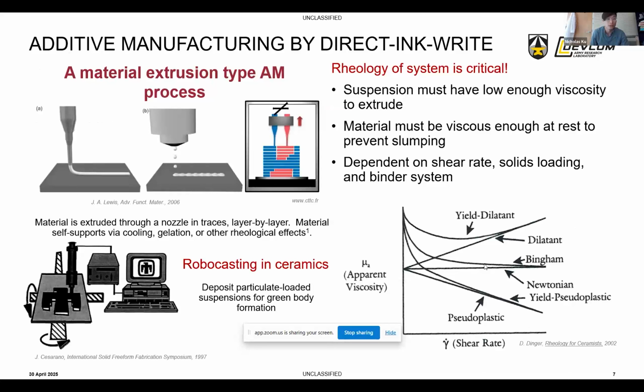So being a direct ink writer, material extrusion type AM process, we do a lot of feedstock development and understanding the rheological behavior. Definitely a big area of research and collaboration that we can work further on. We're concentrating mainly on particulate suspensions. So we're taking powder, water, some organic binder, and creating a slurry-based material, generally about 50% solids loading by volume. But understanding the binder, what kind of solvent is being used, or even going to different non-powder-based feedstocks like pre-ceramic polymers are all of interest, but outside of what we're concentrating on in-house here at ARL.